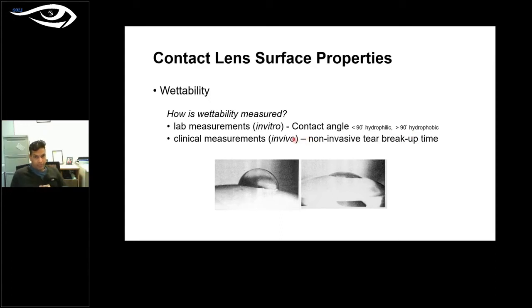And on the in vivo side, that means what we measure on the eye, we cannot directly measure contact angle, but in actual fact, we can measure the non-invasive tear breakup time. There are several ways of measuring non-invasive tear breakup time. One could be using a Tearscope. People these days also use a topographer, a Placido disc type topographer, where you project reflections onto the eye surface and look for any breakage in the contour of the rings. So again, in the laboratory, we measure contact angle. In clinical measurements, we look for tear breakup time. And even though I said less than 90 degrees is hydrophilic, what we want is a very small angle. I'll explain that further in the next slide.